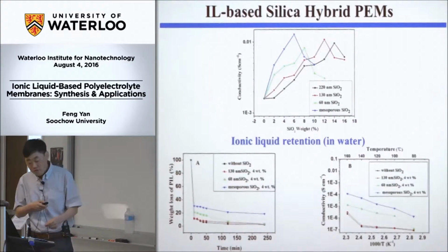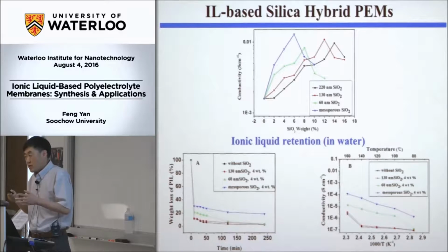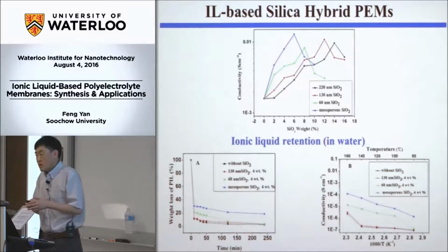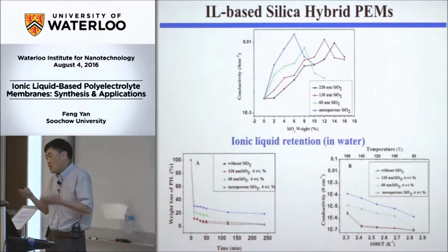Finally, we found that some mesoporous silica nanoparticles can retain around 20% of the ionic liquid inside the membrane. This method can overcome the problem to some degree, but still cannot completely overcome the problem.